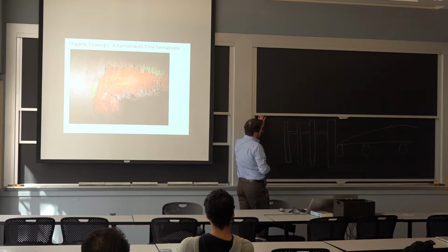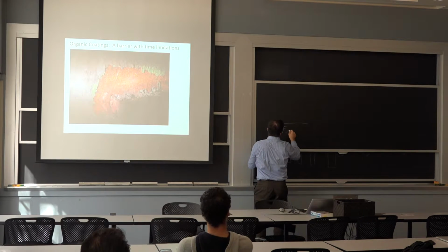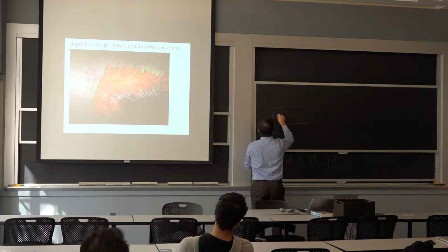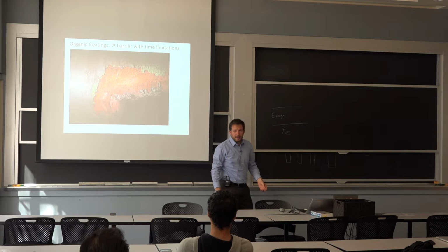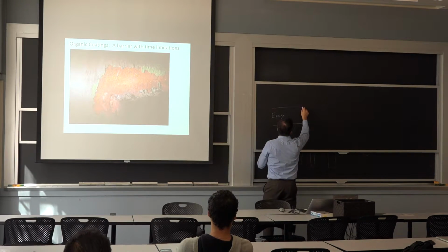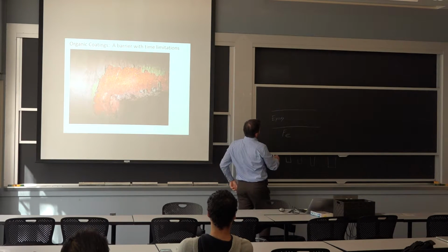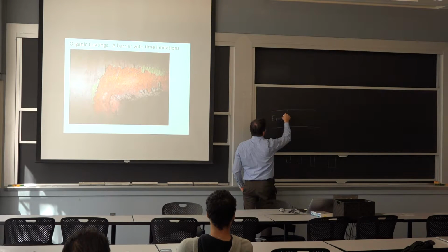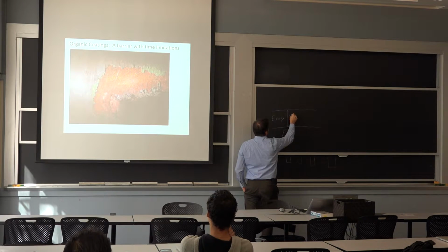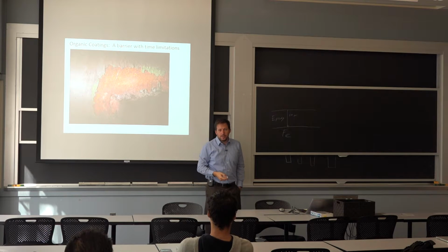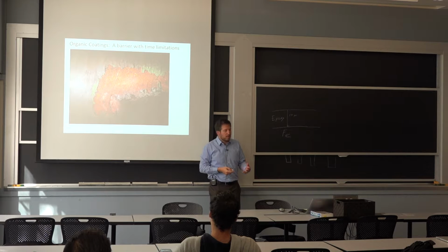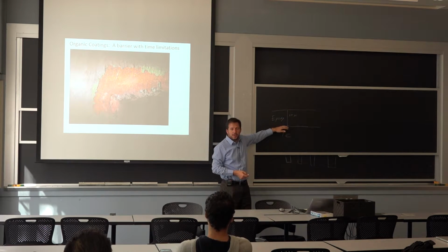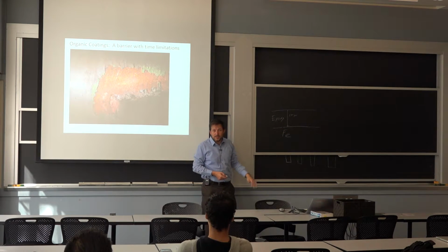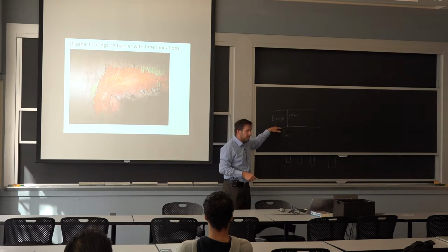So the life of your organic coating, so say we have our steel here, and then we have hard epoxy, because if you're serious and this is really what you want to do, I'm not talking about just painting your bike or something. I'm talking about something that needs to be a long-term solution. They'll optimize it, and with epoxy, if it's properly set and cured, you can have it so it will take up to say 15 years in immersed condition, and maybe up to 25 years when it's just moisture, for all that moisture and oxygen to get all the way to the interface to start the reaction. Now, by the time that the reaction is started, it's gone. Everything is over. You have to reapply and start all the way back from here and do it again.